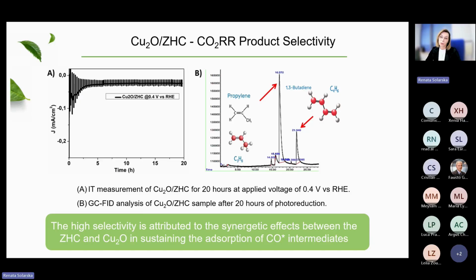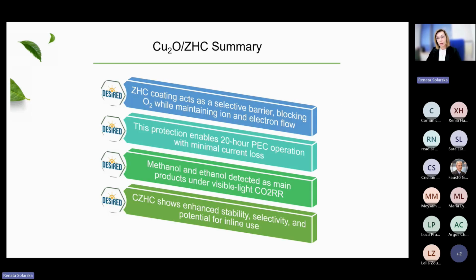So the high selectivity is attributed to the synergetic effect between the zinc hydroxychloride and the copper 1 oxide through the higher energy of the absorption of the CO radical and the CO radical intermediates. So in summary, I would like to say that the coating of zinc hydroxychloride can be deposited in a very simple way by photodeposition. However, it's very effective by creating the intimate contact with the copper 1 oxide, can protect, block the oxygen, and maintain the ion exchange and electron flow in the bulk, and therefore this is a very good co-catalyst, I would say, and can be used for production of higher hydrocarbons.